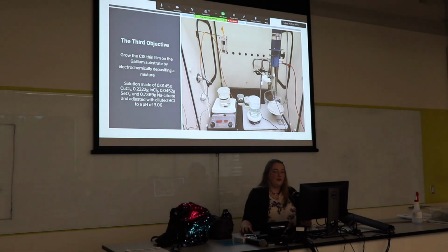So the third objective was to grow our film. We have our device over here, which will electrochemically deposit our solution. Our solution is made of copper chloride, indium chloride, selenium oxide, and sodium citrate. And the film tends to grow in a more acidic environment. So we did adjust it to a pH of 3.06 using diluted hydrochloric acid.